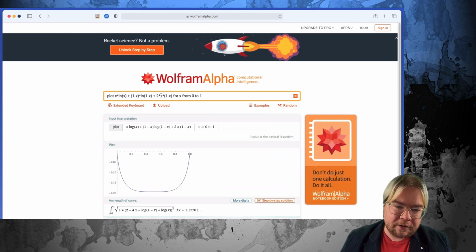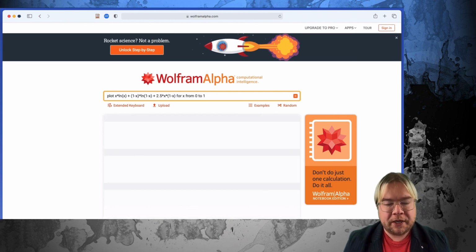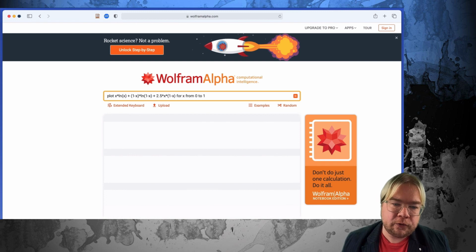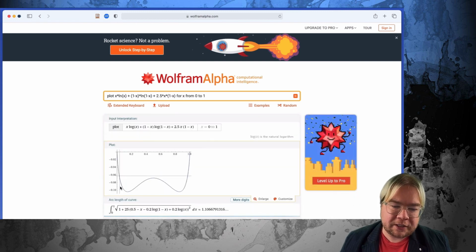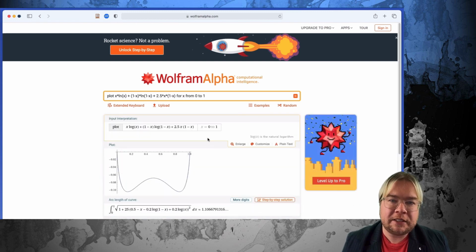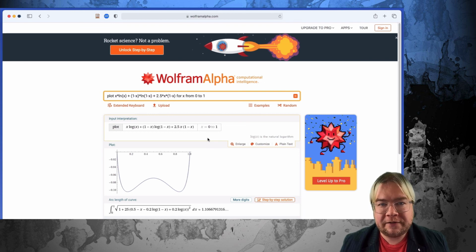And so here's a value of the chi parameter of 2, and you see that the system is still probably going to mix together, but it doesn't take very much above 2 to get to the point where I start to develop this W shape and I start to have regions of instability. So in the next video, what we'll talk about is where those regions of instability are, what's going to happen to our system at equilibrium and how we might think about blending these polymers together even though they don't like each other.